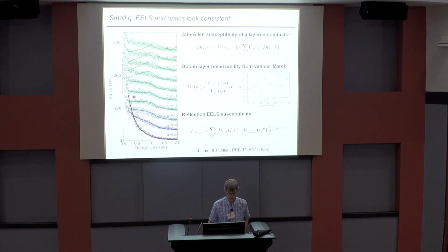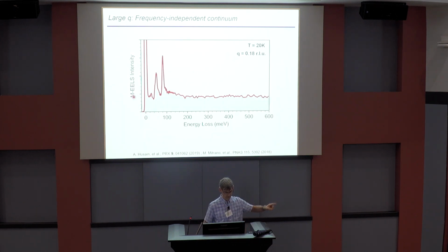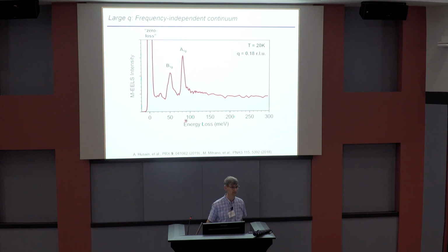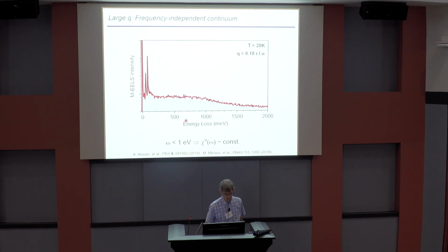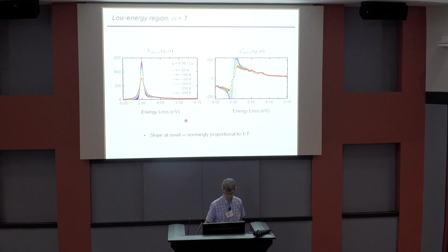So we've spent quite a while trying to go down and measure this low energy region where omega is of order T. By doing a lot of extra work, we've been able to get better energy resolution and momentum resolution, and now we can see it, sort of. What is shown on the left now is the low energy region, minus 50 meV to 150. And this is the correlation function. That's what you measure in the experiment. To get the susceptibility, you have to anti-symmetrize that.